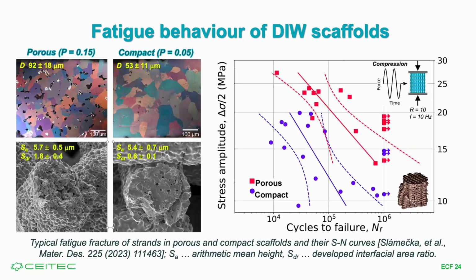The samples we tested were cylinders like this, and when you look at them, you cannot say if the microstructure of these filaments is this or this. They look the same, but the fatigue behavior is different. So what we can do is try to optimize porosity. This is one thing we can try to improve fatigue life even more, and the other, which I'm going to talk about, is that we try to improve crack initiation life by using nitridation.